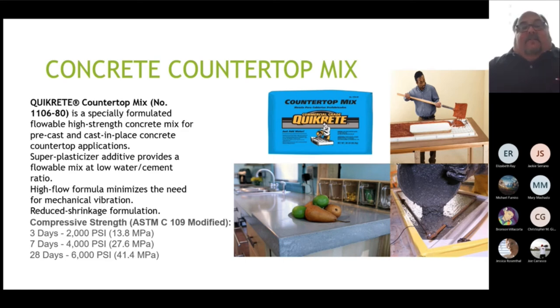Or I've seen them where they've actually polished them out. It's like a 7-stage polish, and the thing is like a bowling ball. It was black and it was incredible. It was beautiful. But stay under 2 inches. You start trying to pour like a 4-inch countertop, it's going to crack. So make sure that your substrate, your cabinetry, or whatever you're putting on can support the weight of all that concrete, because it is concrete after all. It's going to be really heavy. It's just a great product.